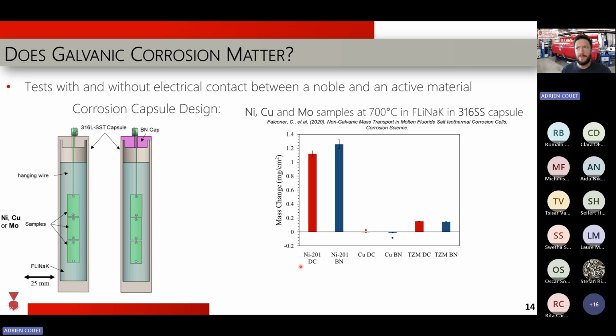And then, surprisingly, with the experiment, we see an increase of the mass. We don't see a loss, right? So that was a little surprising to us, especially nickel, which is supposed to be pretty inert, has gained quite a bit of mass in this experiment. And clearly, this is not something you would expect from galvanic corrosion, right? And when you look at direct contact, so the DC is direct contact, the BN is this boron nitride insulation, you don't see a difference, right? Very little difference when you use nickel, copper, or moly. TZM is kind of 99% moly. You don't see a difference between electrical contact and no electrical contact, and in most cases you see weight gain.